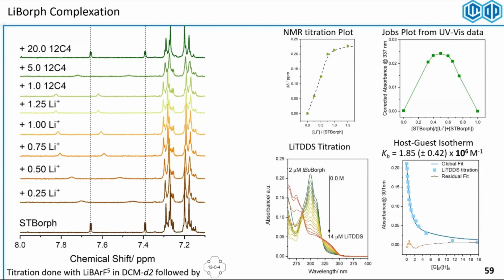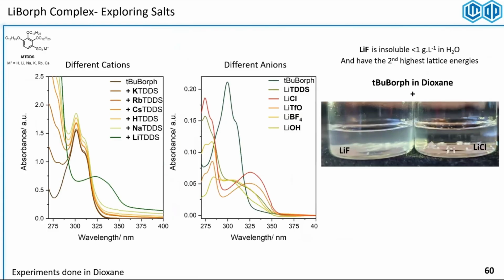But we had to put almost 20 equivalents of 12-crown-4, which is one of the most well-known lithium-binding macrocycles, to be able to extract this lithium back from the macrocycle. So we had close to 20 times more binding affinity to the lithium with this macrocycle as compared to the conventional crown ethers. We studied different methods to make sure it's a one-to-one complex. What would be the binding constant? We found that it's on the order of millions in ether, which is one of the highest numbers reported for lithium binding in etheric solutions.